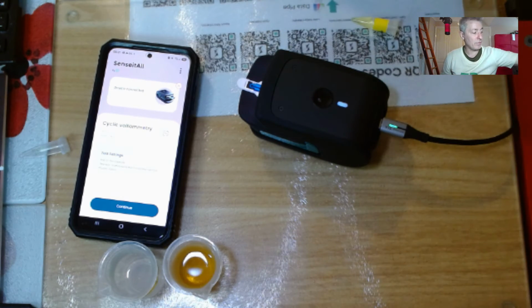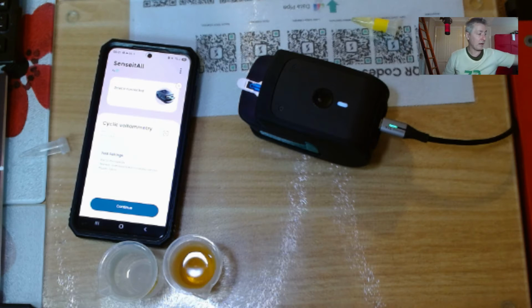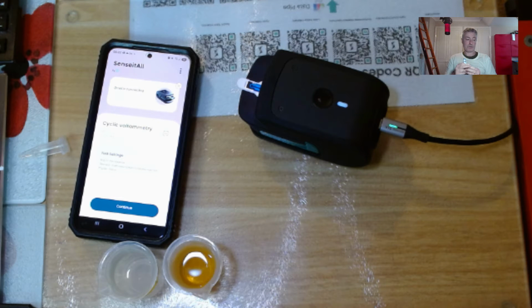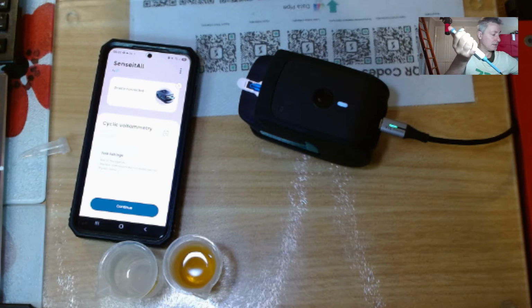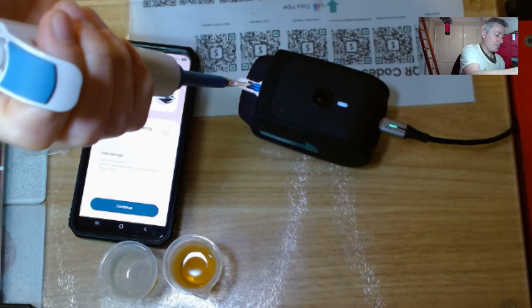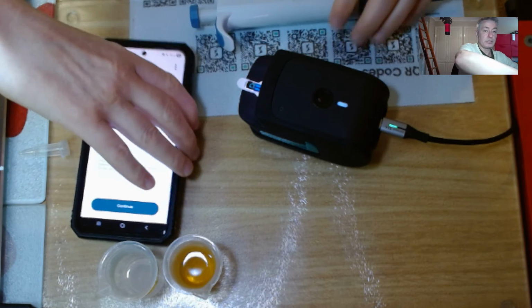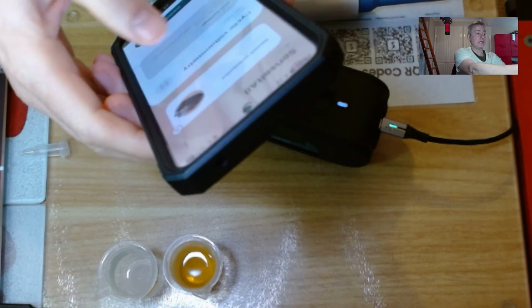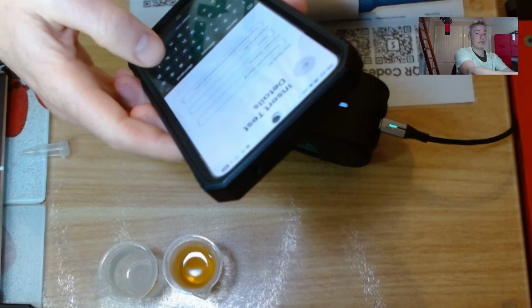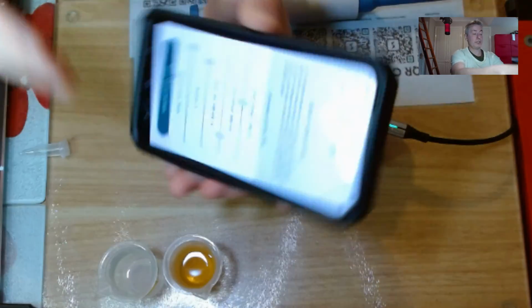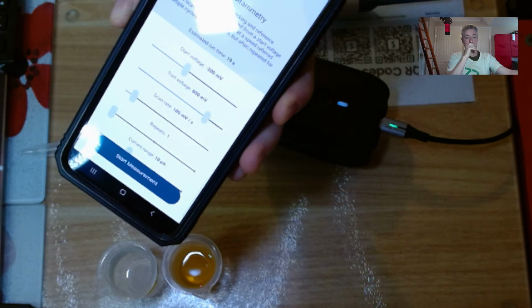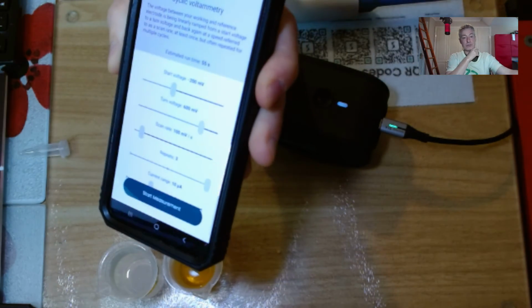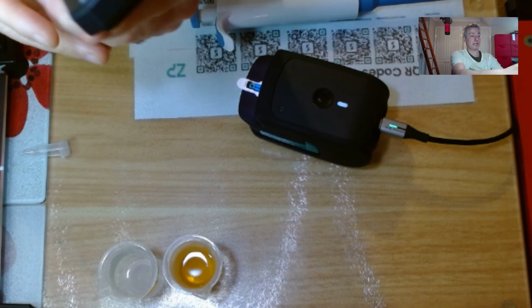I'm just going to take a 5 millimolar ferricyanide solution and do a quick piece of voltammetry on that electrode. So 5 millimolar ferricyanide here. Right, I've grabbed the 5 millimolar ferricyanide. I'll put it on. I'll make sure I name it in the app so I can find that data. Ferricyanide demo, so I can find it quite readily. And I'll go continuous. I'll start at minus 200 millivolts. I'll go to 600 millivolts. I'll set the scan rate quite fast. I'm going to do 3 repeats, so 3 cycles. I'll set the current range to 100 microamps and I'll hit start.